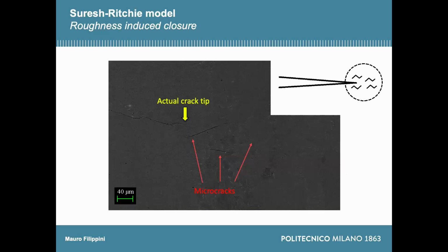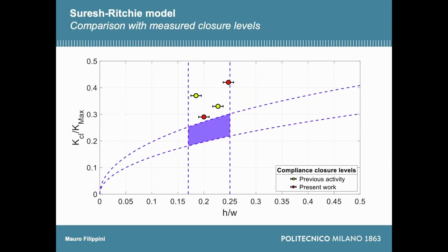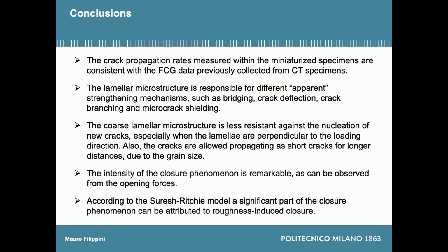And the reason is that you don't have just roughness-induced closure, but you have other mechanisms taking a role, which is crack shielding. You have small cracks forming around the actual crack tip that are somehow masking the loading at the crack tip. And so you have another crack closure effect that is very hard to model in this case. So the new data are also in line with the previous data that we had in initial activity on this side, and this confirms that the pure geometrical, the pure roughness-induced closure system is not capable of explaining everything.